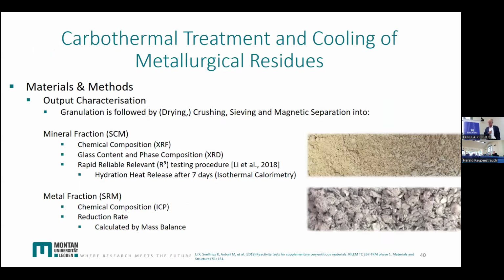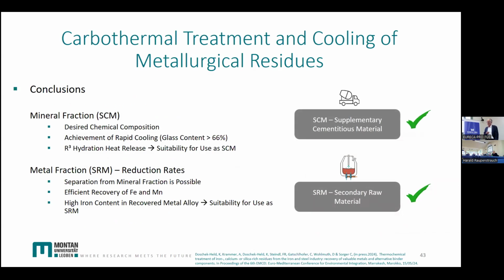So we treat this material and then we characterize the output. For the mineral fraction, the chemical composition, the glass content, and for the cement industry, this R3 testing procedure is important. And for the metal fraction, the chemical composition and the reduction rate. The details you can find in the uploaded complete presentation.